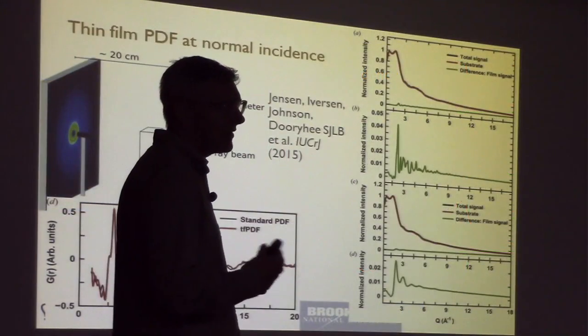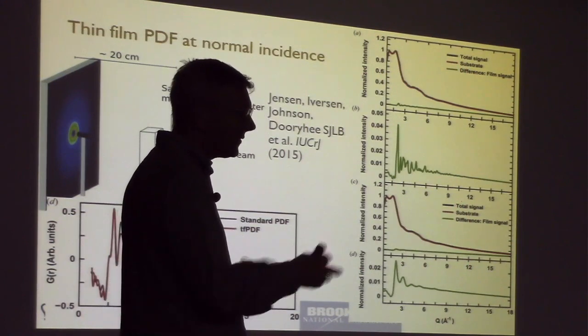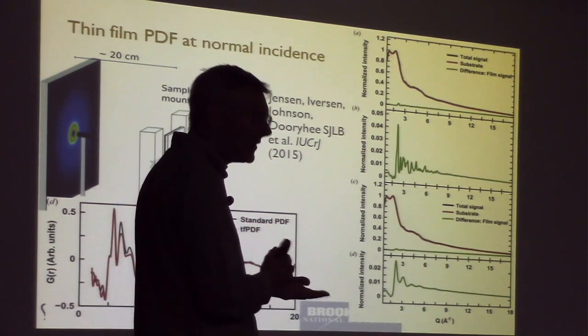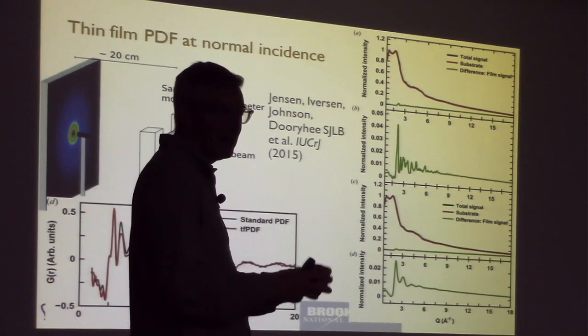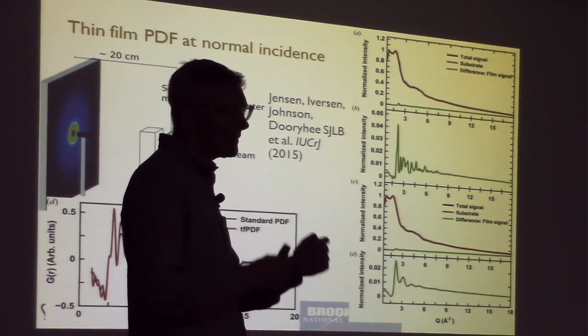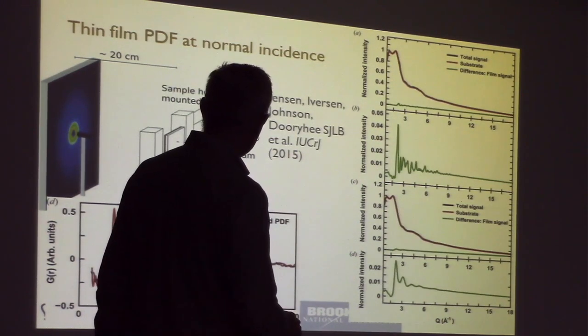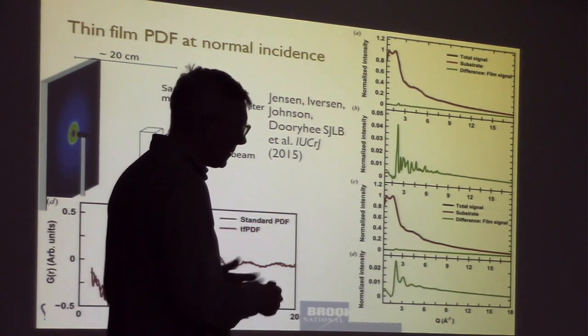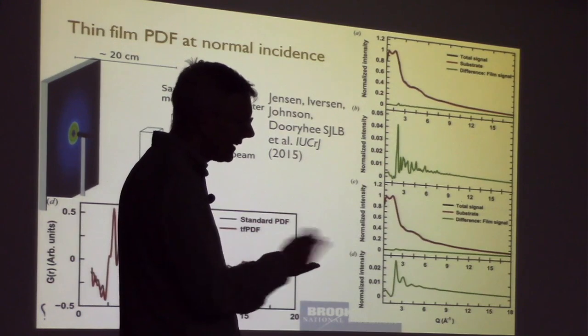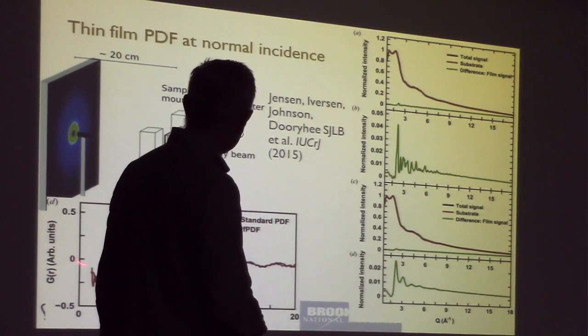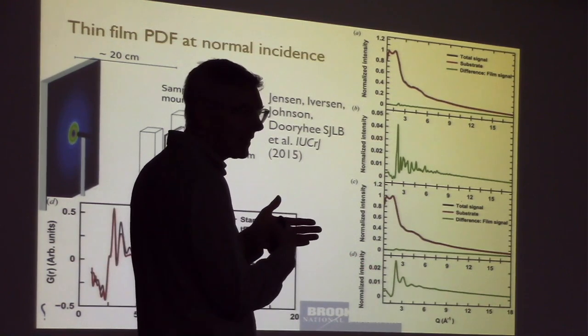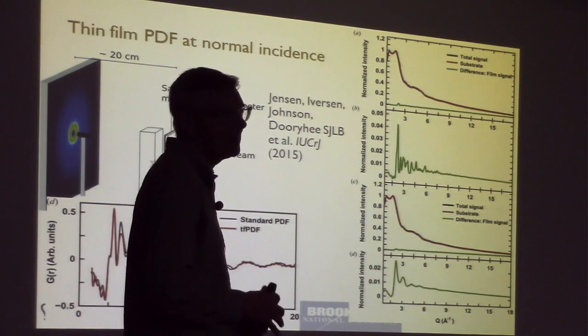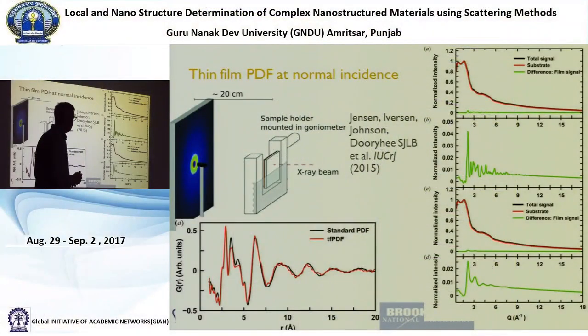And to check whether we weren't just measuring rubbish, what we did is we took many of these films, and we scraped the film off the substrate, and we harvested the powder, and we put the powder in a capillary, and we measured the capillary using regular PDF. And that's the black curve. So the film that was scraped off and put into a capillary, and we did it from like many films to get enough material, is black. But the one that's actually measured just by going through the film is in red, and you can see that we're actually measuring it beautifully. So we're now doing thin film PDF, and the thinnest film that we've managed to measure is 70 nanometers thick, so less than 100 nanometers thick film. So that's an exciting development.